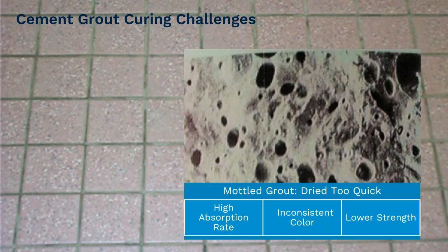We did talk about some of the grout curing challenges we had, specifically with a mottled grout. The image on your screen is an image of a grout that dried too quickly, so it does show that mottled look. So that really came from a high absorption rate. You see the inconsistent color as well as you'll see the lower strength. So this is kind of an idea or a picture we wanted to show you of what a grout can look like when it's mottled because of the fact that it dried too quick.